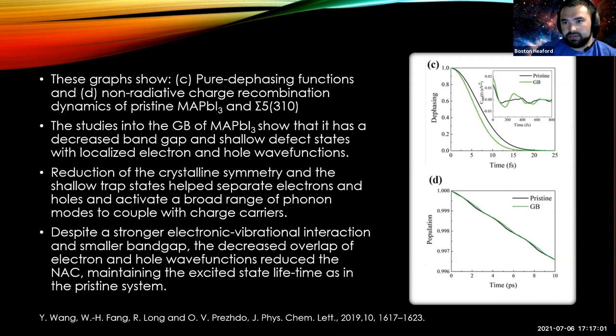pristine system. So it shows that the grain boundaries don't really have that large of an effect on the carrier lifetimes, at least in the methylammonium perovskite. So that's a pretty interesting result. It actually conflicts with a lot of experimental evidence.